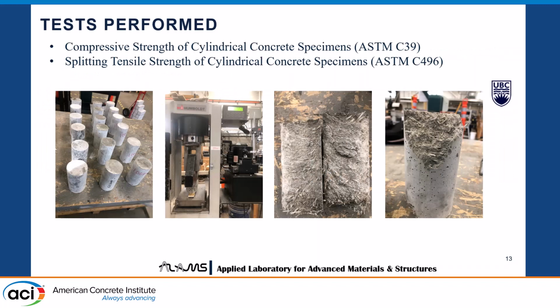We also did the traditional compressive strength test and also the splitting tensile strength test of the cylindrical GFRC specimens. So in the third picture, we can see the sample after tensile test, and in the fourth picture, we can see the sample after compressive strength test.